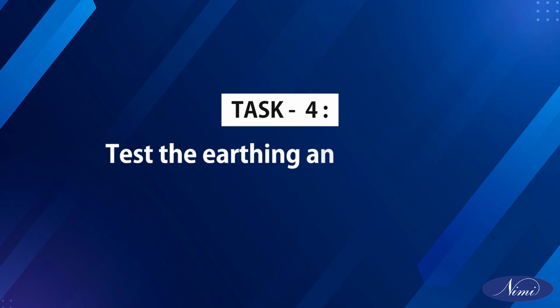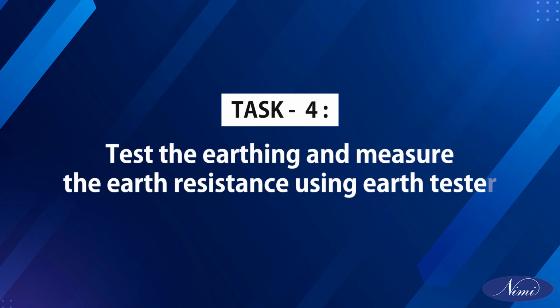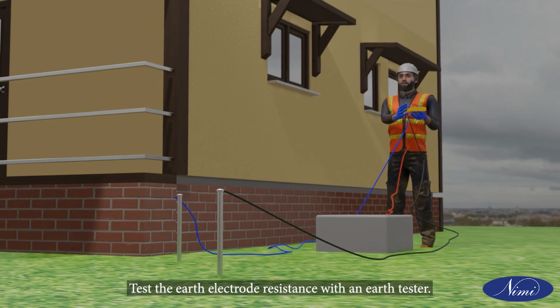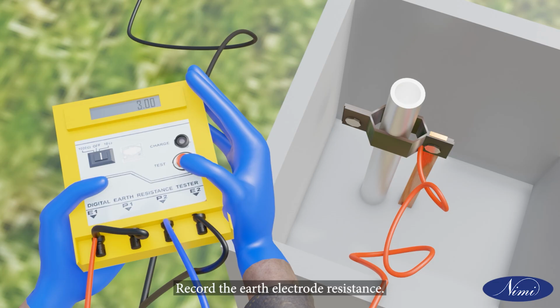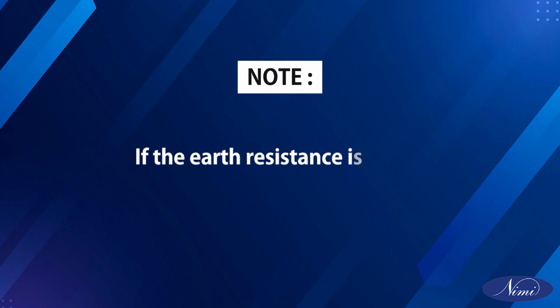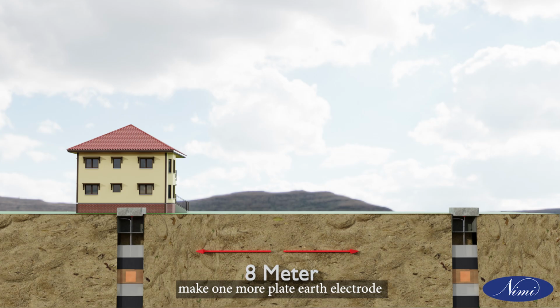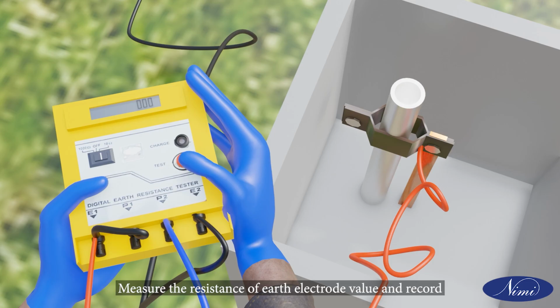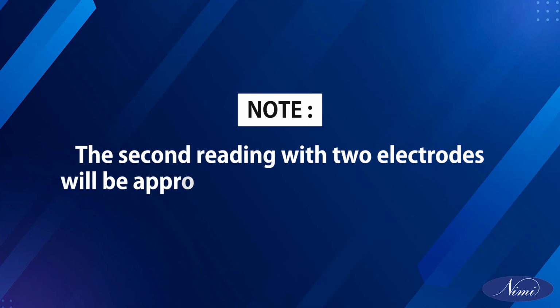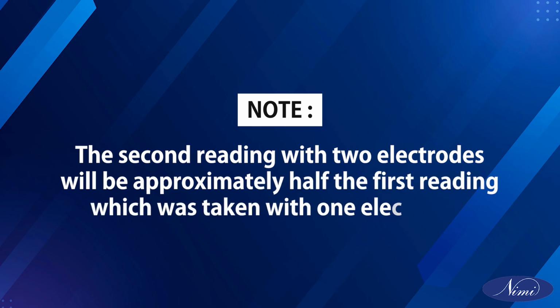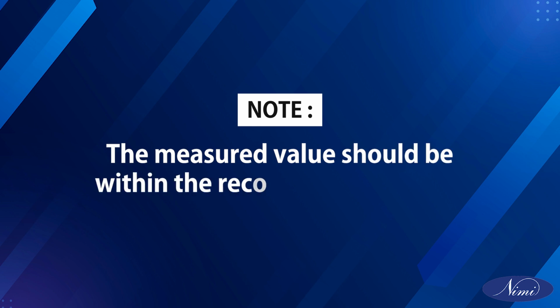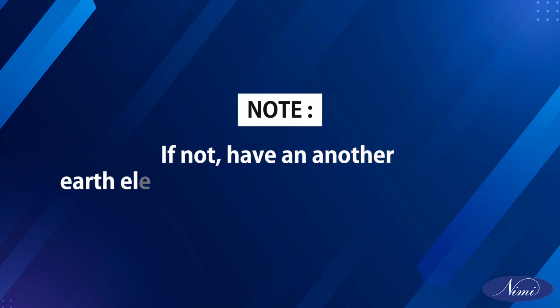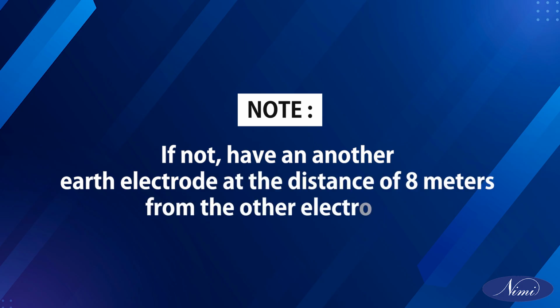Task 4. Test the earthing and measure the earth resistance using earth tester. Test the earth electrode resistance with an earth tester. Record the earth electrode resistance. Note: if the earth resistance is found higher than the acceptable value, make one more plate earth electrode at a distance of 8 meters from the earth electrode and connect both of them in parallel. Measure the resistance of earth electrode value and record. Note: the second reading with 2 electrodes will be approximately half the first reading which was taken with 1 electrode. The measured value should be within the recommended value. If not, have another earth electrode at the distance of 8 meters from the other electrodes.